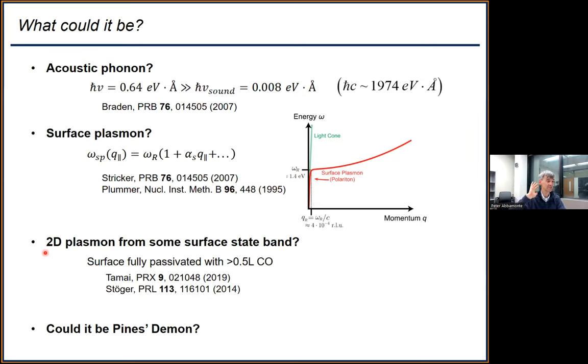And it turns out strontium ruthenate has a surface state. If you cleave it at cryogenic temperatures, there's a broken bond that's sticking up and you get a partially filled band there. But it turns out it gets instantly passivated by any amount of carbon monoxide in the chamber. And our system had quite a lot of carbon monoxide. And there's several papers on this. So basically that thing would be passivated. We wouldn't be able to see it.